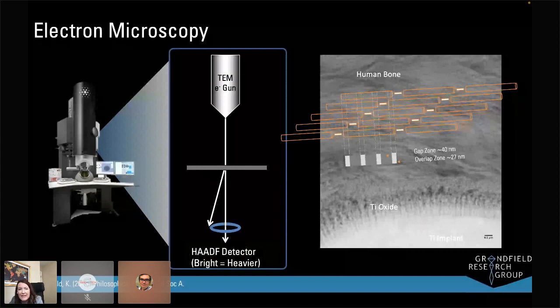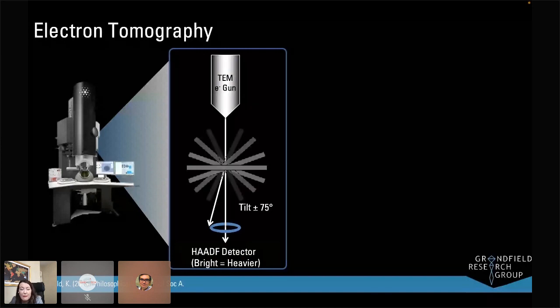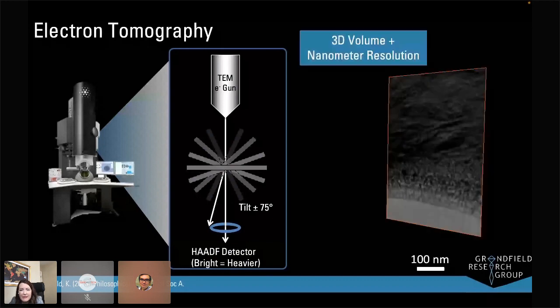So let's take a step further and look at 3D first. Inside the TEM, we can take this thin section and we tilt it. So you can imagine it's something similar to X-ray tomography, except we're using electrons. And when we perform this, we can create a reconstruction by similar methods of algorithms to reconstruct 2D images into a 3D volume.